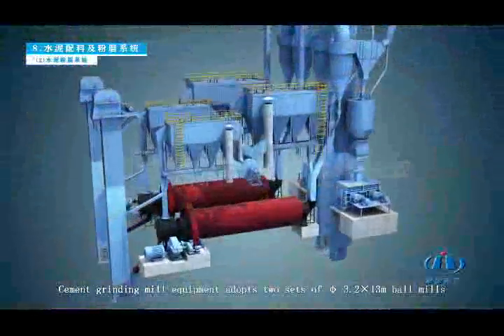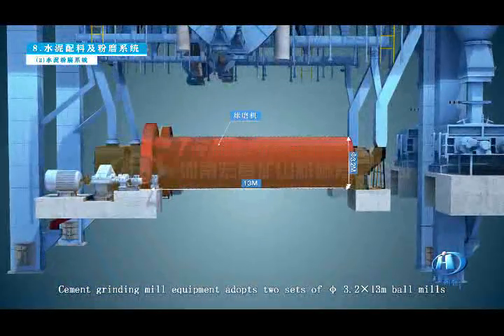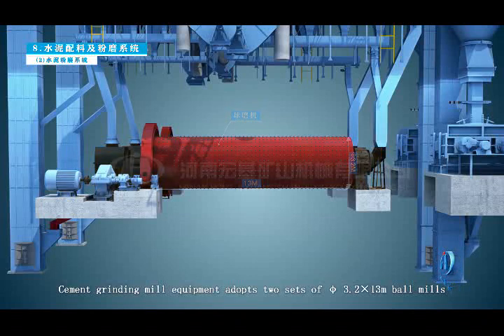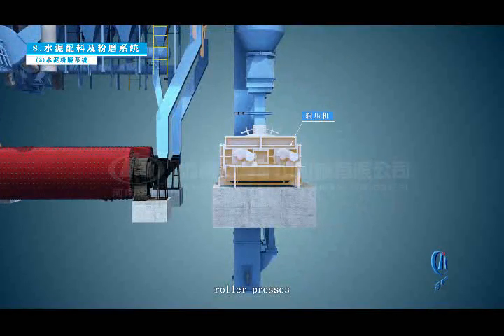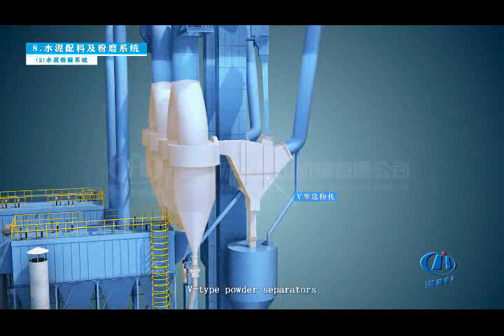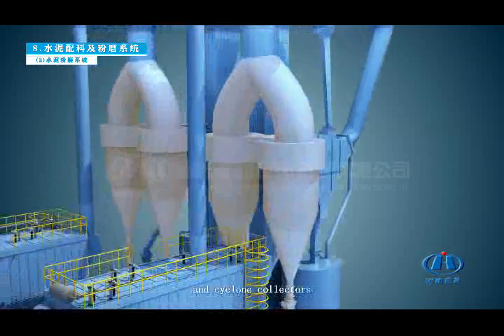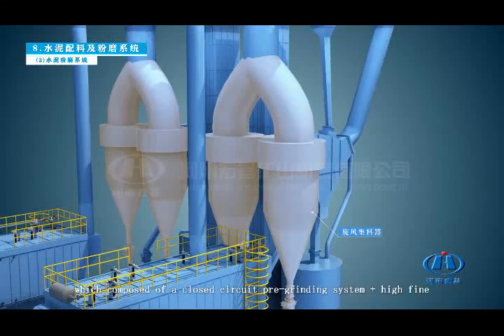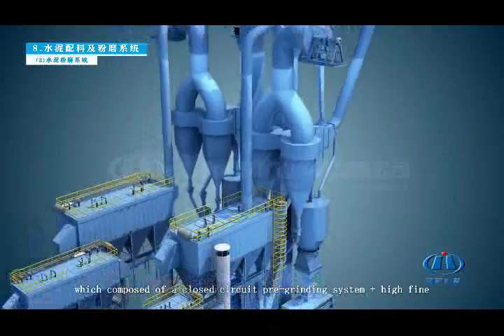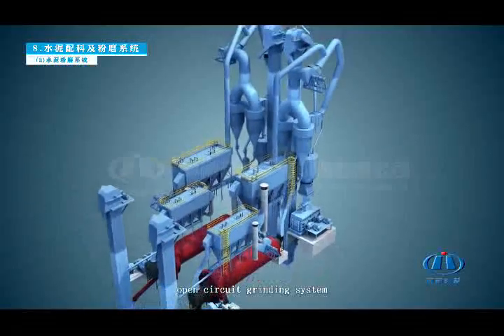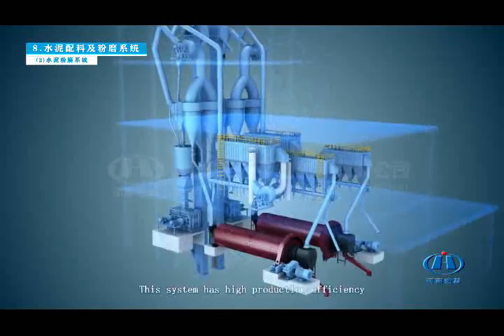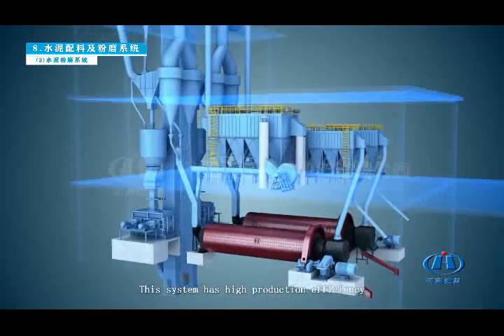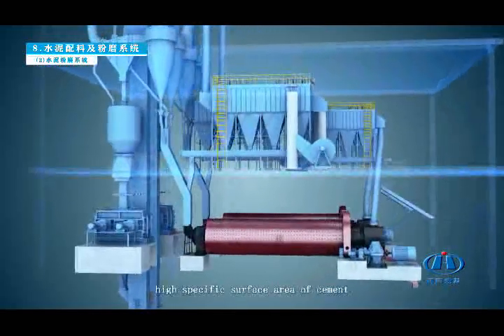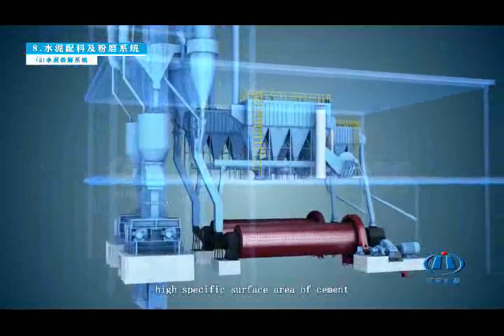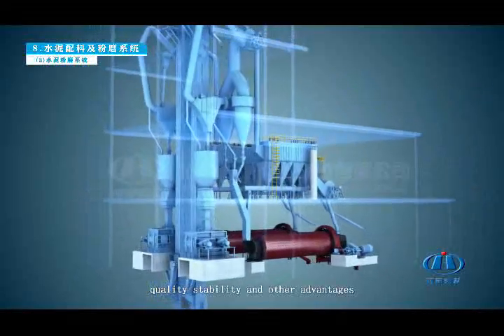Cement grinding equipment adopts two sets of 3.2 by 13 meter ball mills, roller presses, V-type powder separators, and cyclone collectors, which compose a closed-circuit pre-grinding system plus a high-fine open-circuit grinding system. This system has high production efficiency, low energy consumption, high specific surface area of cement, quality stability, and other advantages.